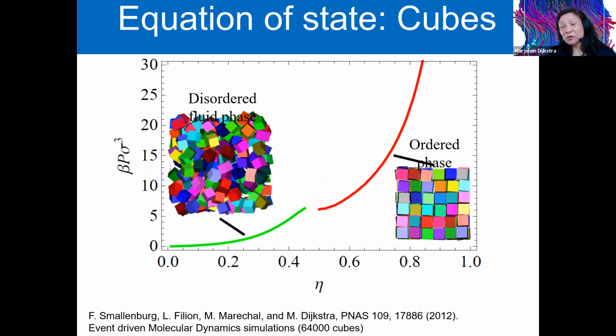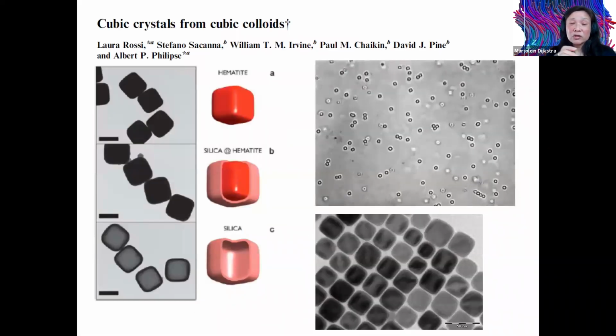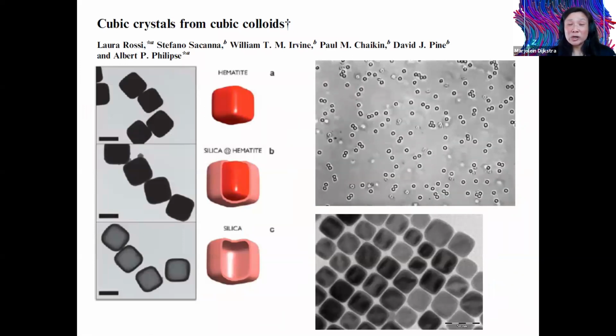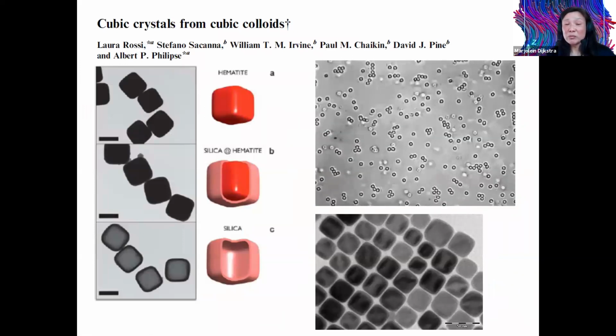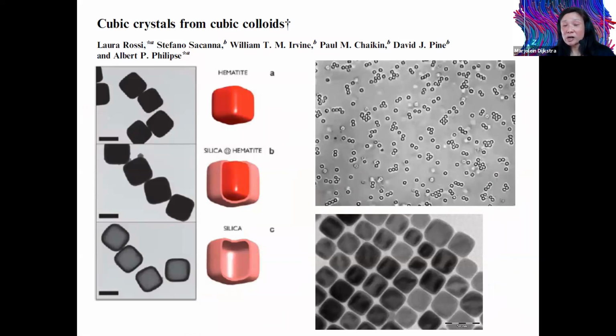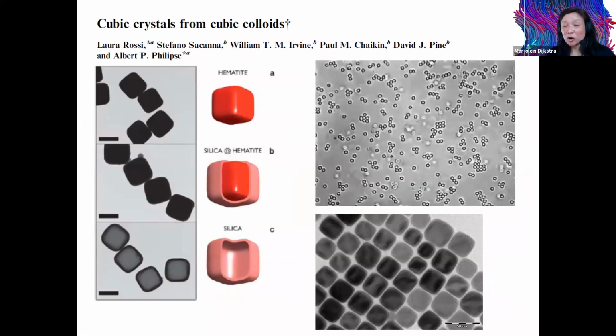Another particle shape we've looked at is that of hard cubes. They form a simple cubic lattice, and this fills 100% of the space. But if you look, for instance, at the colloidal particles, which are made using hematite cubes and then growing silica around it, they are slightly rounded.